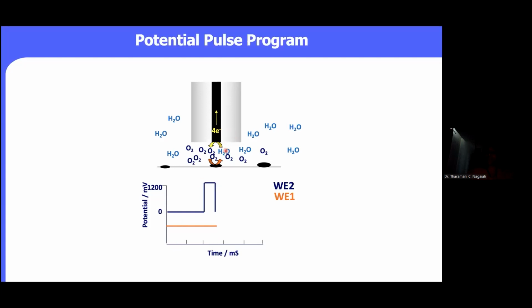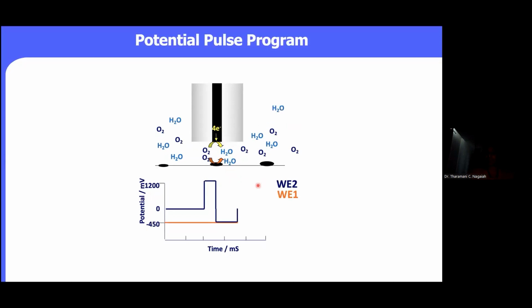So by applying a potential, that means we know that electrochemical water splitting, we can split at 1.2. So therefore, we have enough oxygen in the gap between the tip and the substrate. So now this is very important, as you can see here. So this we call the redox competition mode of SECM. So that means both the tip and also the samples are competing for the available oxygen in the gap. If the catalyst is strong enough, it consumes oxygen and reduces it to water. And so therefore, we are measuring the current at the tip.